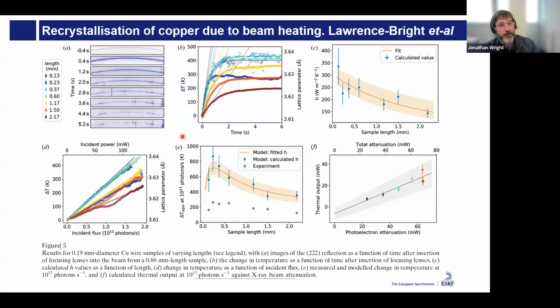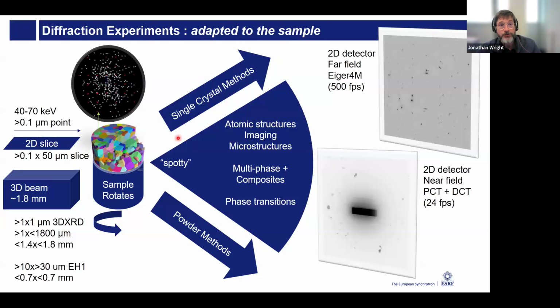So Eleanor developed a detailed model of these different processes and how this was happening. And so in practice, we normally have much less absorption in the samples. We spread the beam over a larger area, or we have better thermal conductivity for cooling. And it's not normally a problem. But if you do need a lot of flux, we usually have sufficient flux for most things that people want to do. So what kinds of diffraction experiments do we do?